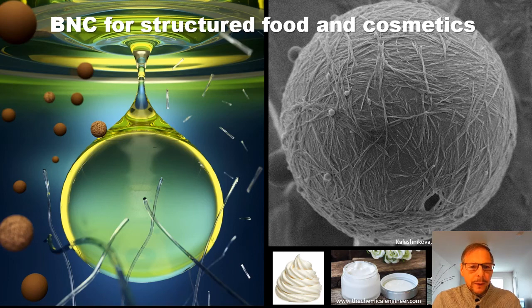So an emulsion droplet in the case of the left will be oil droplets dispersed in water, and the bacterial nanocellulose that I have introduced will go to the surface of the droplets, stabilizing those droplets, protecting the droplets, and from that, applications such as the ones in the bottom for food and cosmetics will be very easy to perform. And this is very nice because bacterial nanocellulose is known to be biocompatible, non-toxic, and safe. So it can actually be used for us to eat.